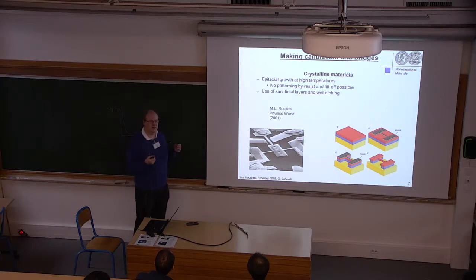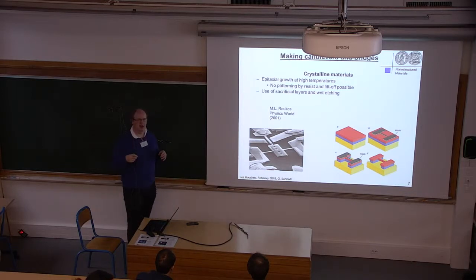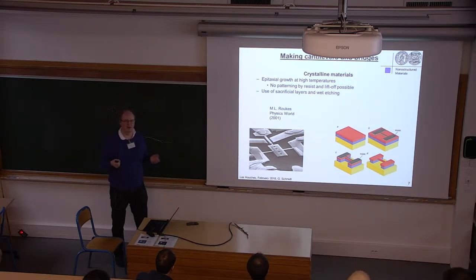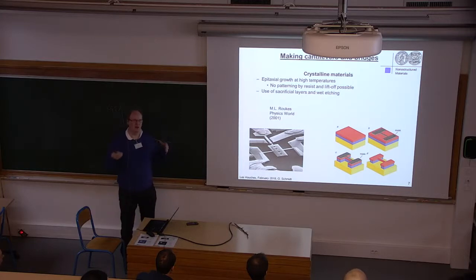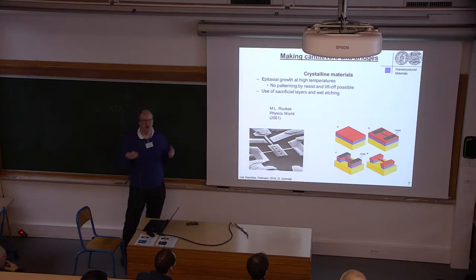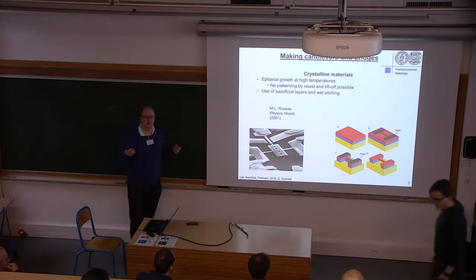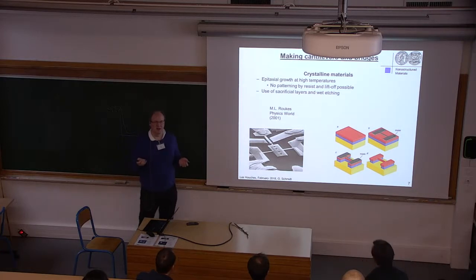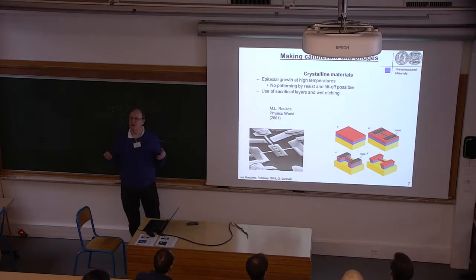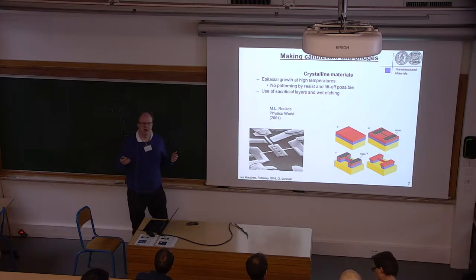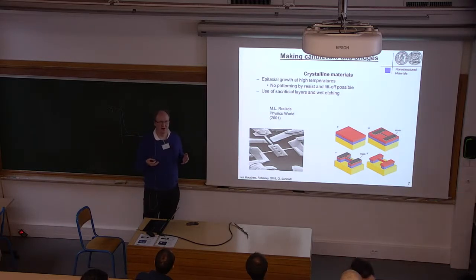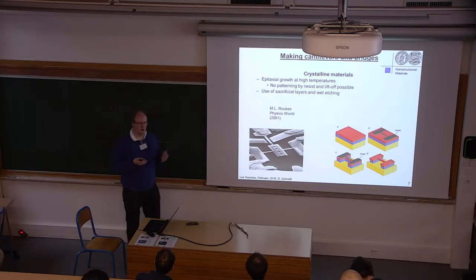We want to have something where we can put lots of oscillators close to each other, and we also need to preserve the properties. Normally you look for mechanical resonators where you just want them to be mechanically stable to have the right properties, but in this case we also want the magnetic properties to remain the same. And YIG is a crystalline material, and if, for example, you use ion milling or focused ion beam, it may well be that you damage the material, and if you make a very small device and you damage the material, then it's quite likely that the physical properties will degrade.